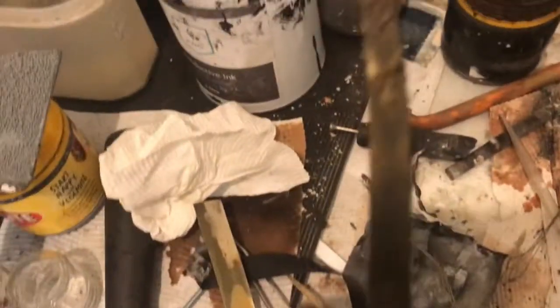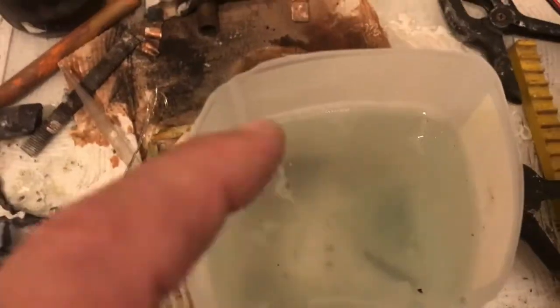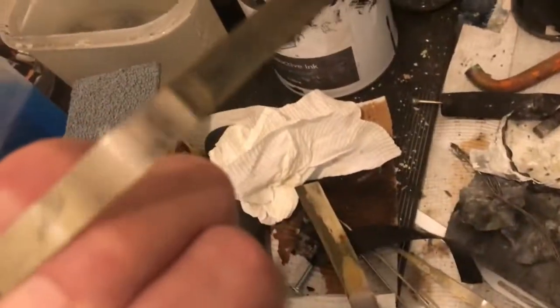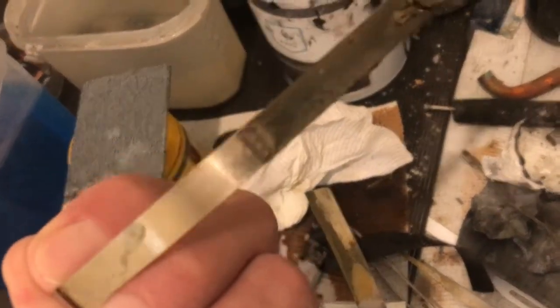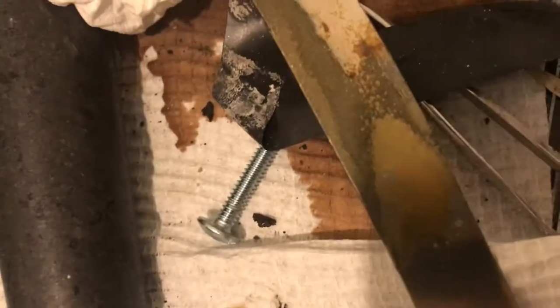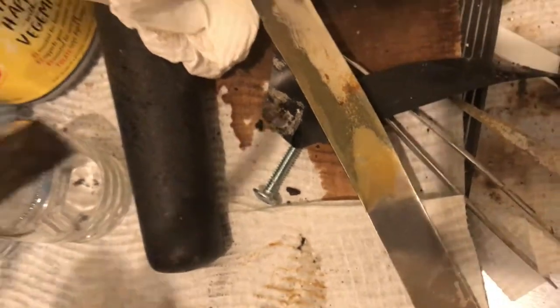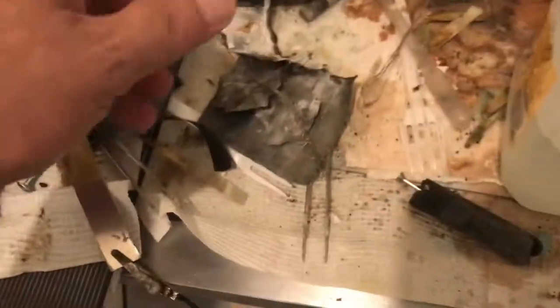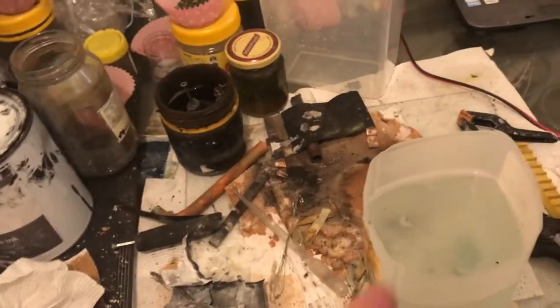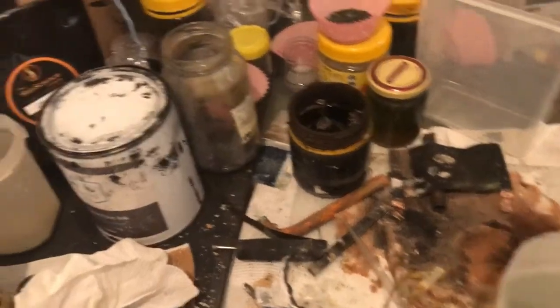This is one which isn't nickel, and you can see the difference clearly. There's probably a bit of contamination on there. I'll wipe that clean from being in this solution for an hour with these things. These things are definitely not nickel. It should be plating that colour really, or somewhat that colour without this contamination. So buy your nickel, test it. Bad, report to the seller ASAP.